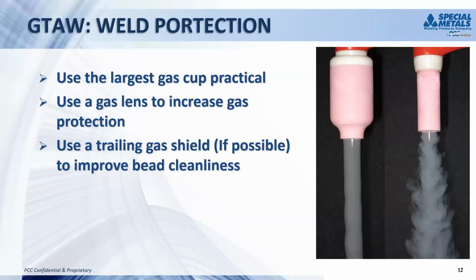So we mentioned the gas protection. One of the things we really recommend is the shielding gas lens, and then also using the largest gas cup that's practical. I always say practical because it would be great if you could use, you know, a 6-inch diameter gas cup to just flood that and keep that weld protected. However, you just may not be able to reach into a groove.